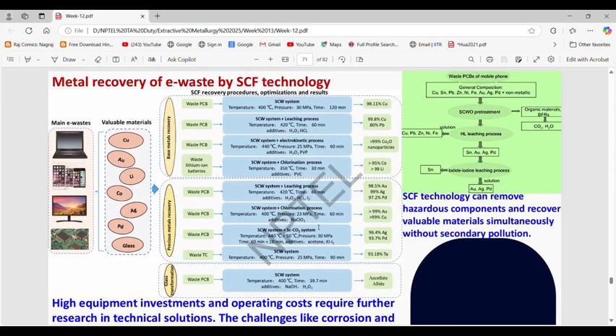Then coming to the metal recovery from e-waste by supercritical fluid technologies. Some base metals can be recovered by these technologies, like from waste PCBs using a supercritical water, SCW, system at a temperature of 400 degrees Celsius. Supercritical water system has been applied for the recovery of copper at a temperature of around 400 degrees Celsius with a pressure of 30 megapascal, and within 2 hours we can extract around 98.11% of copper from these